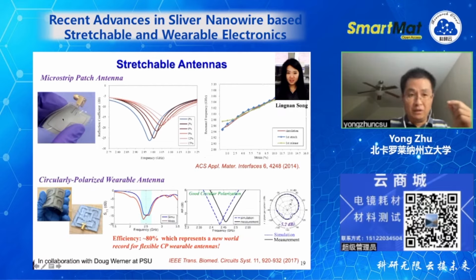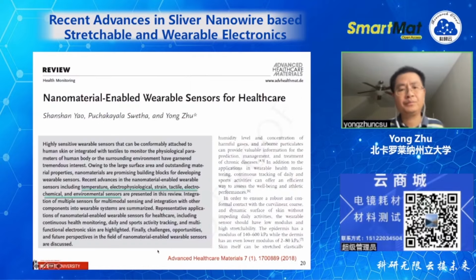This is a very simple design, but with a more complicated, more sophisticated design, we were able to make a so-called circularly polarized antenna. Then we can further improve the efficiency. For instance, we were able to achieve about 80% efficiency, according to our collaborator. This was the world record, at least a few years ago, for the efficiency of flexible wearable antennas.